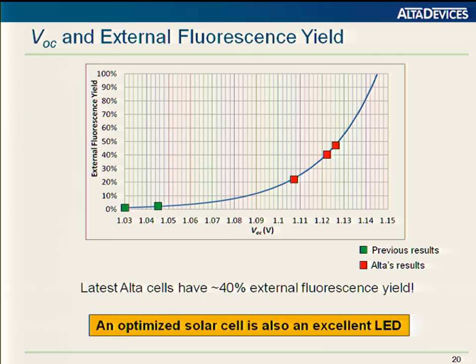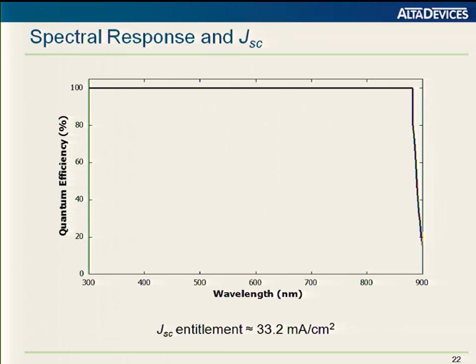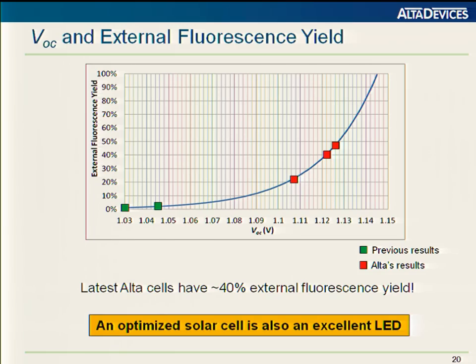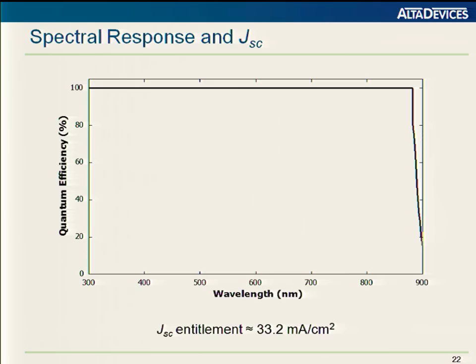This is a point Eli Yablonovitch and others like to make, that an optimized solar cell is also an excellent LED, and we find that to be true for our cells. As far as further performance enhancement then, another point I want to make about this is that the returns become somewhat diminishing. To get to above 50% external fluorescence yield, the change in voltage that's remaining is no more than 30 millivolts, and probably less than that is achievable. To make significant improvements beyond 28.8, we need to look at the short circuit current density.